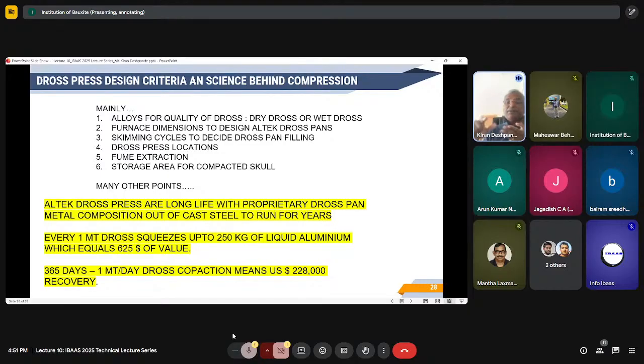What are your skimming cycles? Because your bottleneck is 6 minutes. So if you have one press catering to 4 furnaces, each furnace having 1 cycle, and in 1 cycle there are 2 cycles of skimming and so much dross, that means so many pans, so every pan has to be given justice within 30 minutes of the skimming. So that's a design factor.